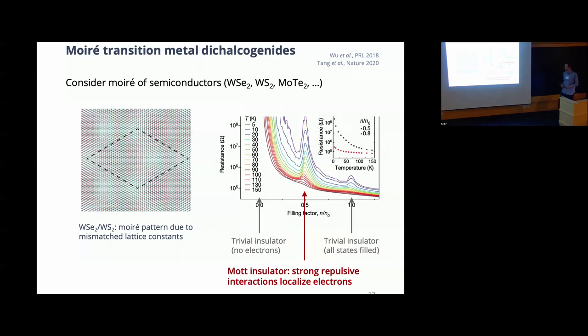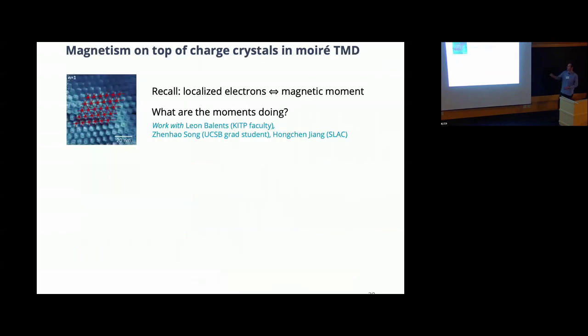This is an extremely non-trivial state where actually the strong repulsive interactions lead to a localization of the electrons. So if all of these red dots strongly repel each other, it actually becomes very unfavorable for them to move, right? So they mostly want to stay as far away as possible from each other, form this periodic arrangement, and not move anymore. Okay, so this is this Mott insulator of electrons. And remarkably, they can even take images of this. Again, this is completely unheard of usually in condensed matter physics because the lattice constants are so small. But now here, because we are talking about, I don't know, 100 nanometers instead of half a nanometer, you can actually take images of these types of configurations.